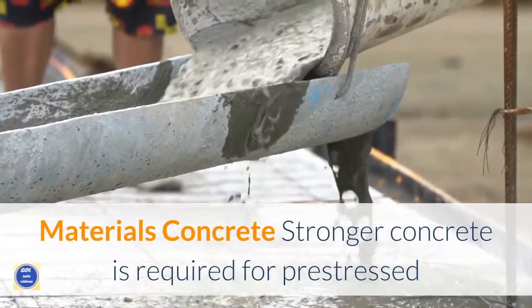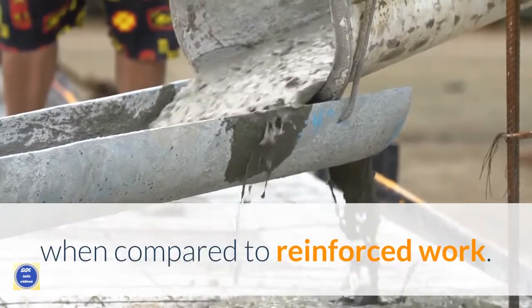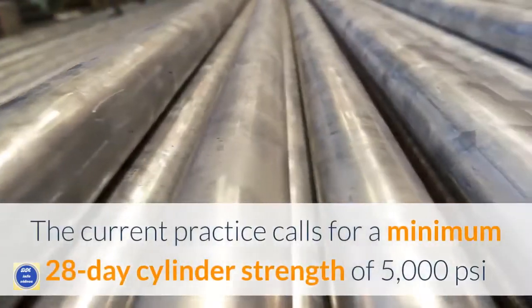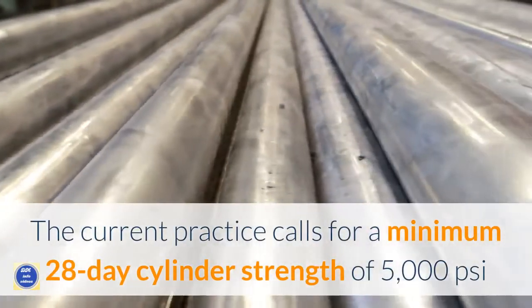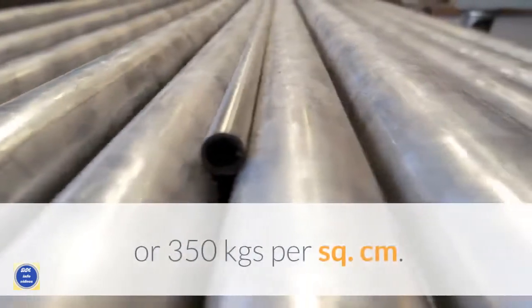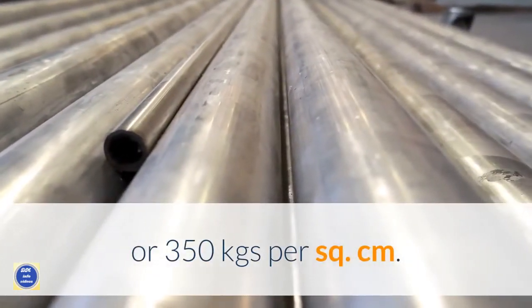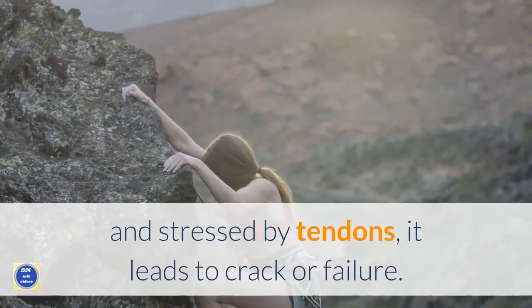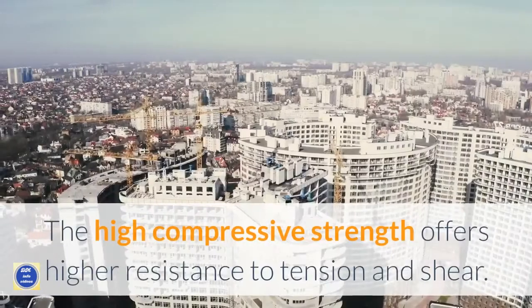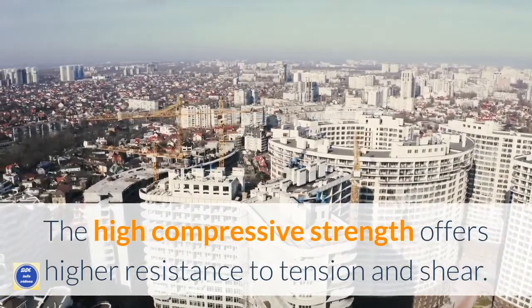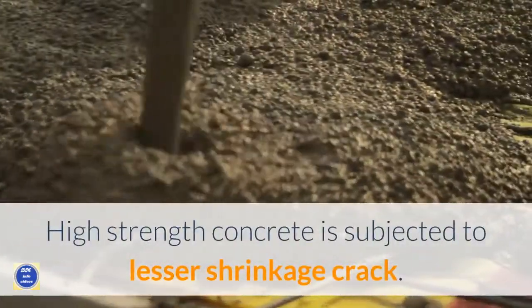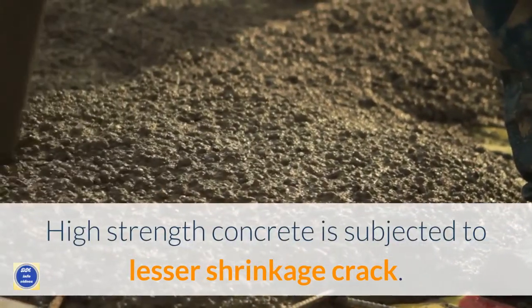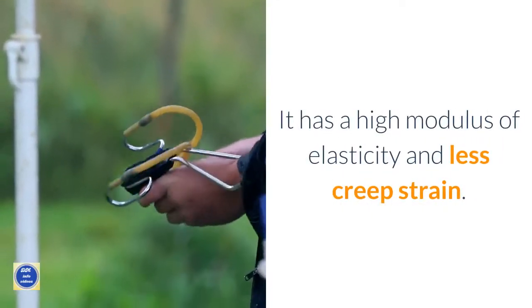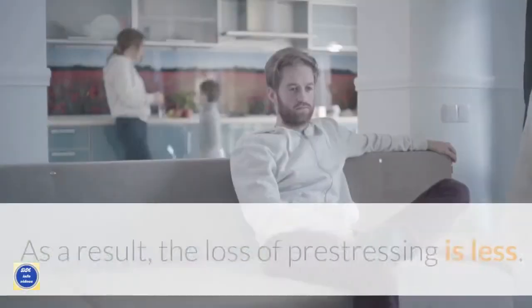Materials: concrete. Stronger concrete is required for prestressed work when compared to reinforced work. The current practice calls for a minimum 28-day cylinder strength of 5,000 psi or 350 kgs per square centimeter. When the concrete is not adequately strong and is stressed by tendons, it leads to cracks or failure. The high compressive strength offers higher resistance to tension and shear. High-strength concrete is subjected to lesser shrinkage cracks. It has a high modulus of elasticity and less creep strain. As a result, the loss of prestressing is less.